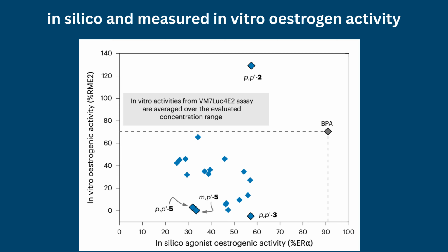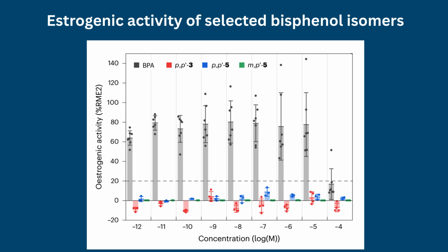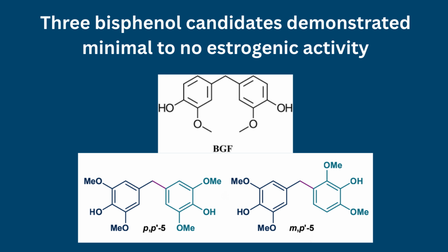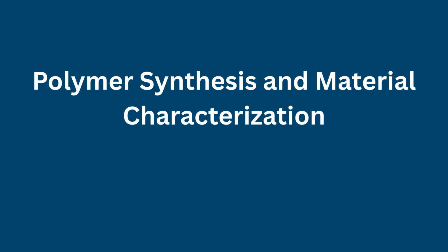Test compounds were evaluated across a wide concentration range, 10^-12 to 10^-4 molar. Estrogen, E2, and BPA exhibited the strongest biological responses, while most synthesized candidates showed negligible activity. Estrogenic potency was quantified relative to E2, with values exceeding 20% considered significant. Three candidates, bis-guaiacol F, BGF, and two bis-4-methoxyphenyl methane isomers, demonstrated minimal to no estrogenic activity, validating the predictive power of the computational screening.